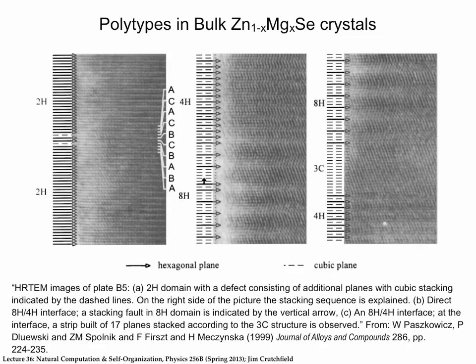This guy right here, and let's not worry about exactly what the ABCs are, but you can sit and work that out in 0-1 notation. But the idea here is that it goes through something that's 2H, it looks like 2H crystal, and again, there's this little region in here where somehow that regular stacking gets broken, and then if we go up here, it continues 2H. So this would maybe be a region that you might want to call faulting. I would think of it as faulting.